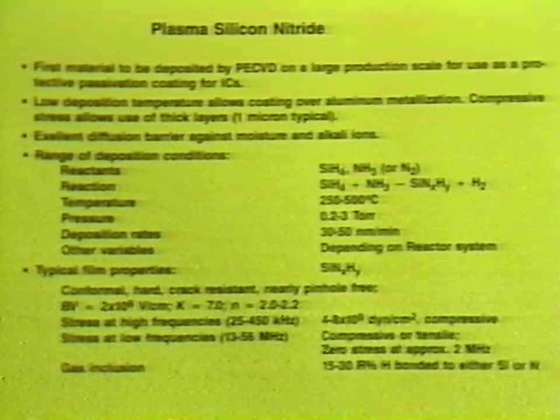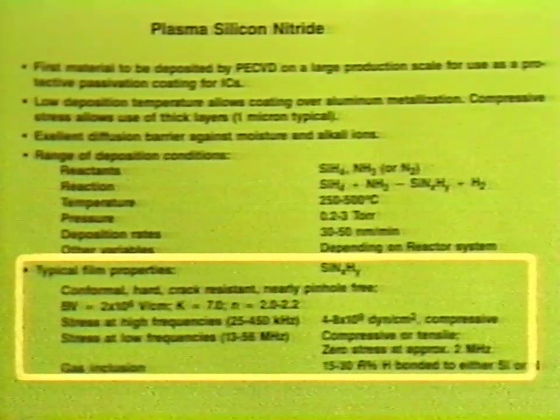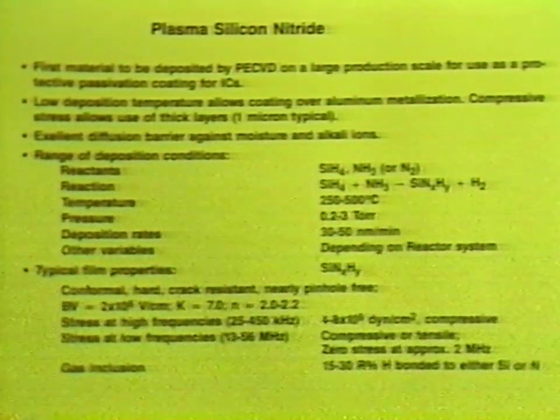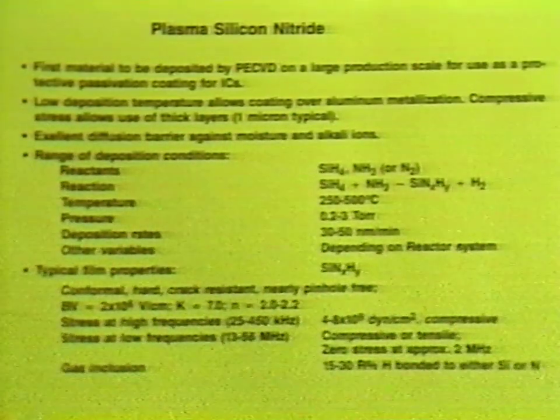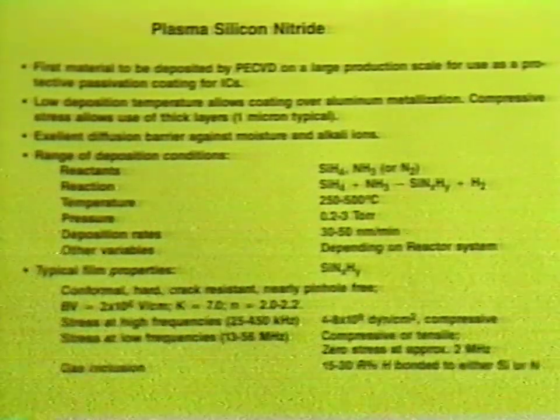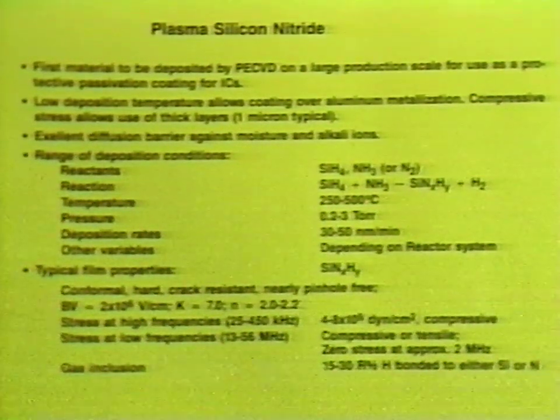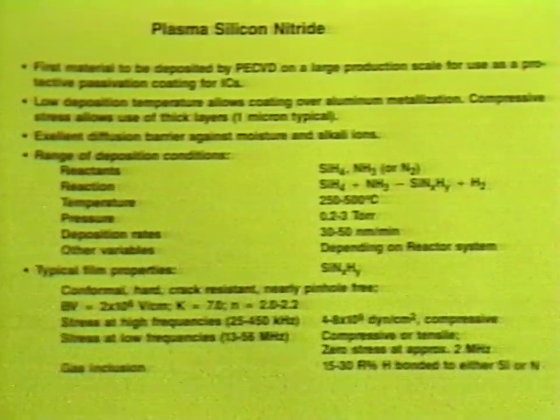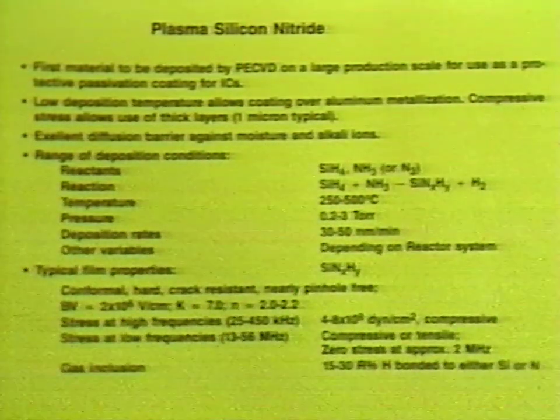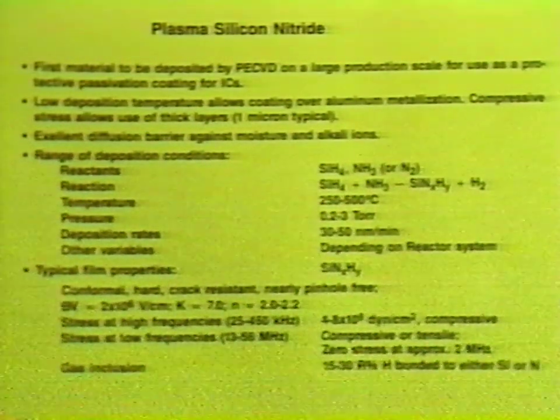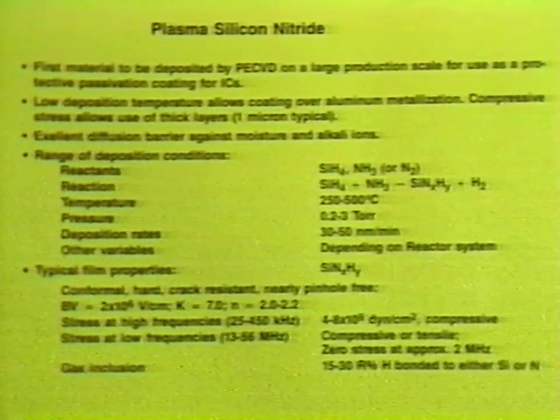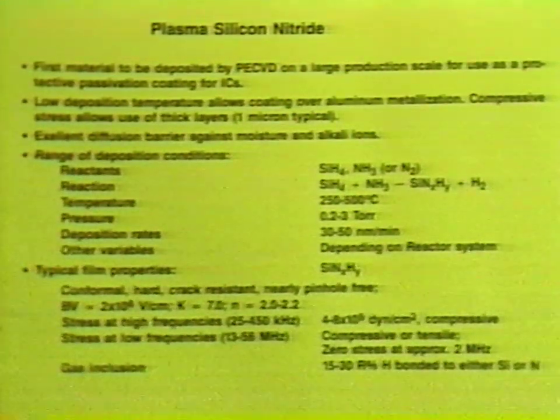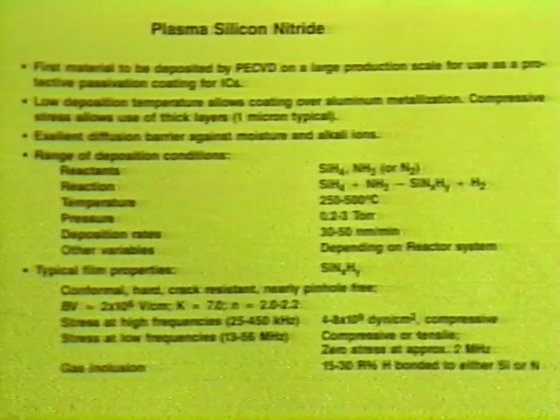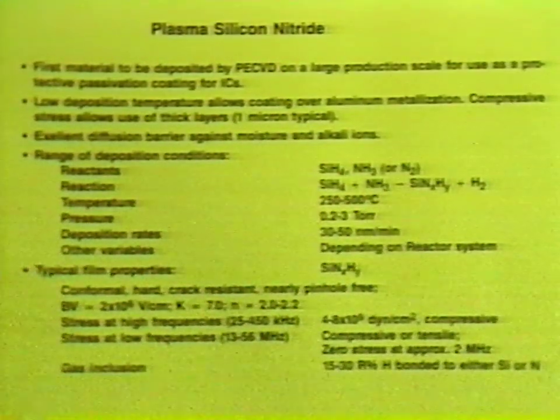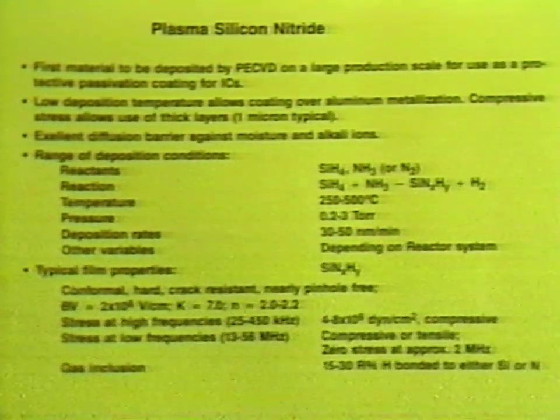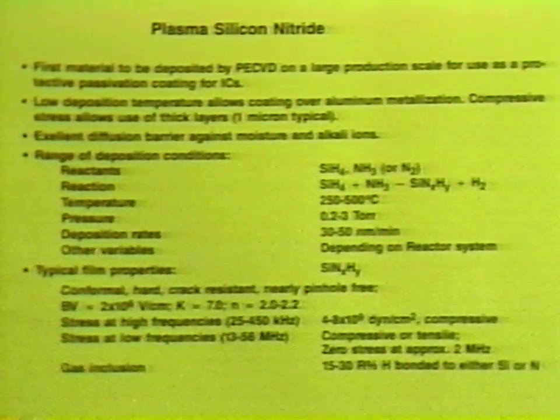The variables, of course, will vary from system type to system type. But the typical film properties are summarized down here. Again, just like the plasma oxide films, they are conformal. These are conformal, hard, crack resistant, nearly pinhole free, with very good breakdown strength and a dielectric constant of about 7 and a refractive index of 2.0 to 2.2. And the stress, as I indicated, is typically compressive. However, there is a variation depending on the type of frequency used for the reactor. In the range of 25 to 450 kilohertz, the stress is typically in the range of 4 to 8 times 10 to the 9th dynes per square centimeter. Compressive, very compressive, more so than we would like to see,